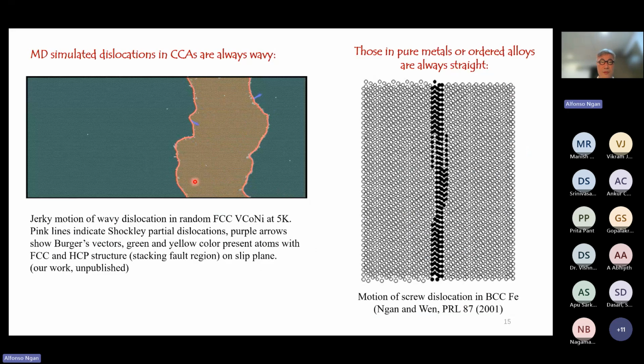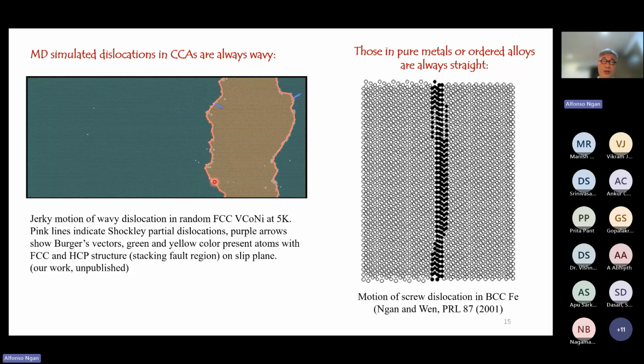And this is some real, not real, but molecular dynamics simulation. So this is CCA, this system, vanadium, cobalt, nickel at 5 Kelvin. And as you can see, the two partials, as they move, they always wiggle in shape.